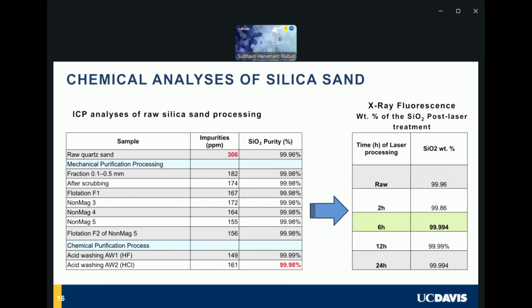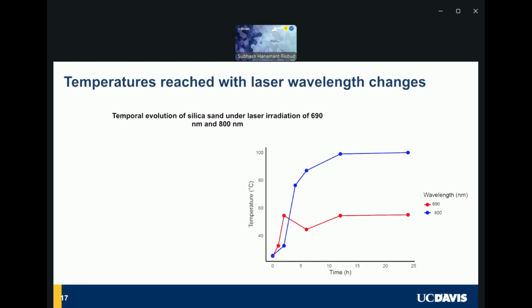And in our laser process, even at something like 2 to 4 or 5 hours, maybe 6, you get very high purity, 99.99. In 12 hours, you just about get the best samples you can get. Now, whether you need this quality of purity or not is another matter. And so we have been trying to see the temperatures reached using different laser wavelengths and playing around with how high temperature you can get and how much time it takes to get the best purity you can get. So this is kind of another project we have ongoing.